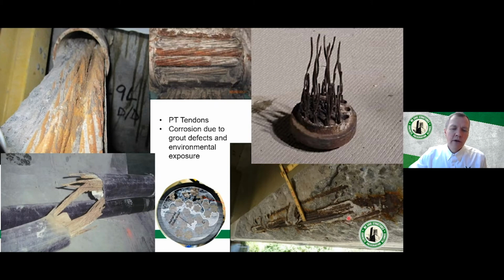And in the bottom right-hand corner, we have an example of a structure that is exposed to chlorides in the environment. This one happens to be a Pennsylvania DOT bridge, and chlorides have soaked through the concrete, gotten down to the metal duct. They've corroded the metal duct entirely, and you can see that the strands inside of the duct are now corroding, and it's led to some concrete damage that is clearly visible.